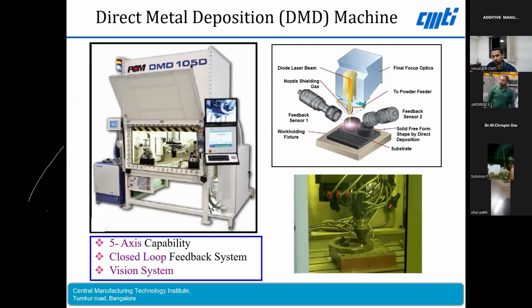Different heat sources could be used. In this machine we are using a laser basically. To monitor the process, you will have sensors like CCD cameras. These cameras will be looking at the melt pool to monitor the layer thickness uniformly, or you can have a pyrometer to measure the temperature and to control the process.